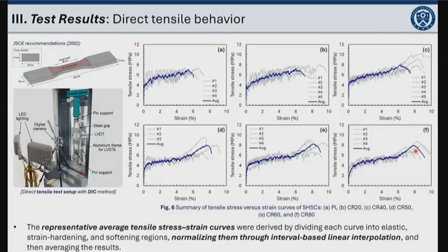Following the Japan Society of Civil Engineers recommendations, we conducted the direct tensile test. Initially, 5 dumbbell samples were fabricated and tested for all tested variables. However, by excluding some specimens that developed cracks at the neck, 3 to 5 specimens were used for obtaining the average data. The tensile stress and strain curves were then averaged by interval-based linear interpolation.